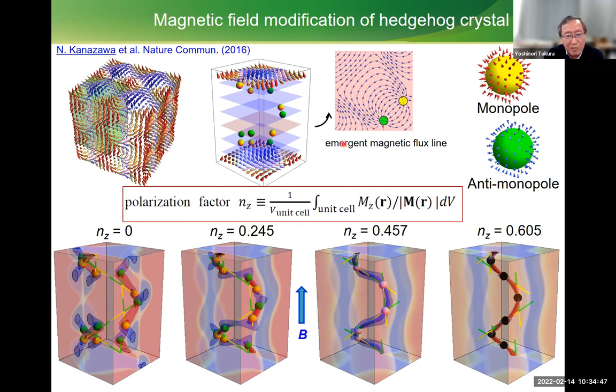And this is just a model cartoon, and monopole, anti-monopole actually show the source and sink of the emergent magnetic flux line. And this flux line is carried by the skyrmion string. But when we apply the magnetic field along, for example, this direction, then one skyrmion just extends and another skyrmion tends to shrink. So originally the total skyrmion number is zero, but with increase of the magnetic field, only one skyrmion just stretches out. And then they maximize the emergent magnetic field. But with further increase of the magnetic field, the monopole, anti-monopole come together. It undergoes a pair annihilation path.